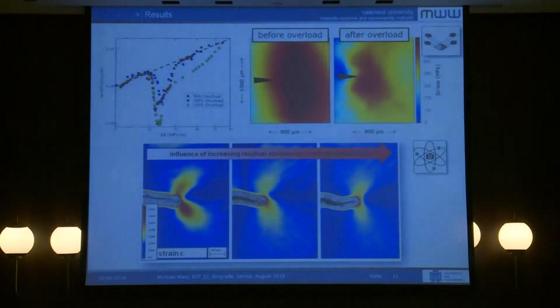Here was the overload, and here is a little bit of fatigue crack propagation after the overload, and you have a reduced strain field at the fatigue load, at the normal fatigue load. This might be somewhere here, and if you have a look here at the maximum retardation, you will have only this very small strain field at the crack tip during the maximum load.